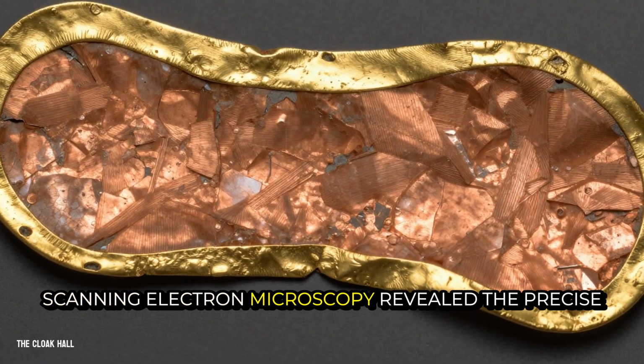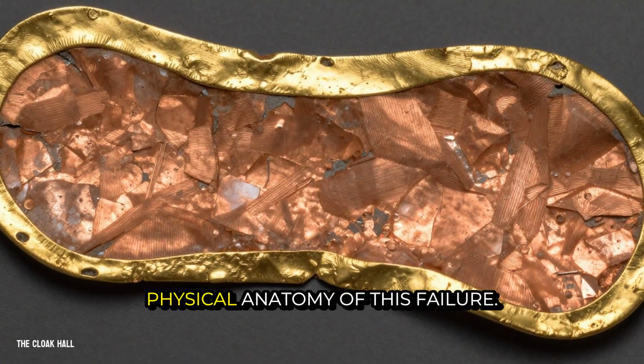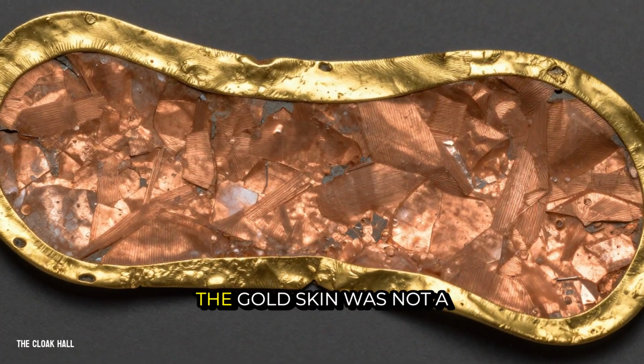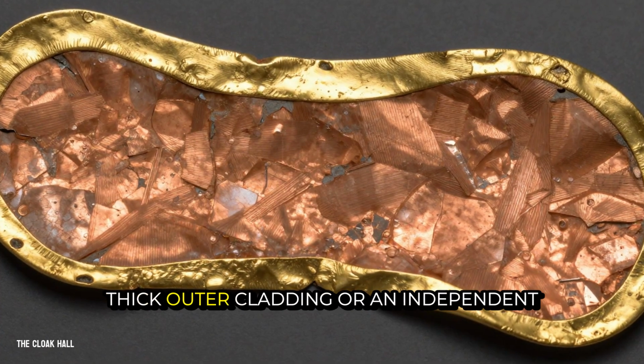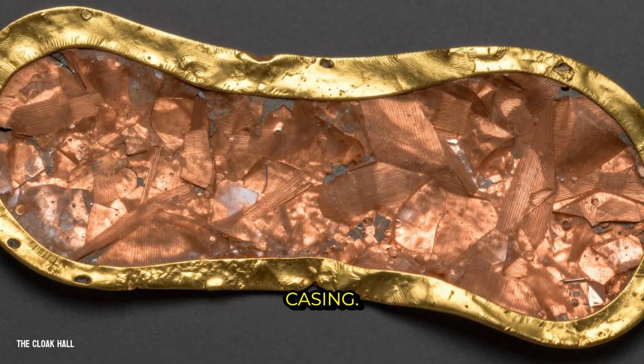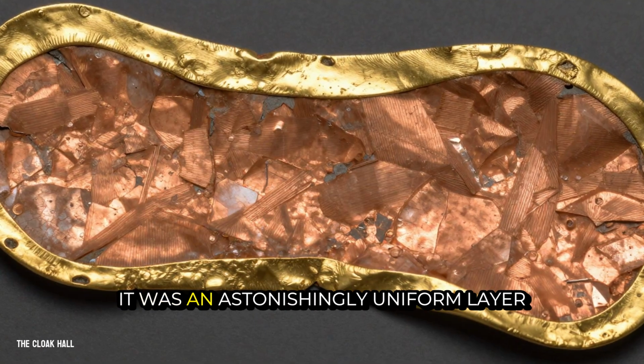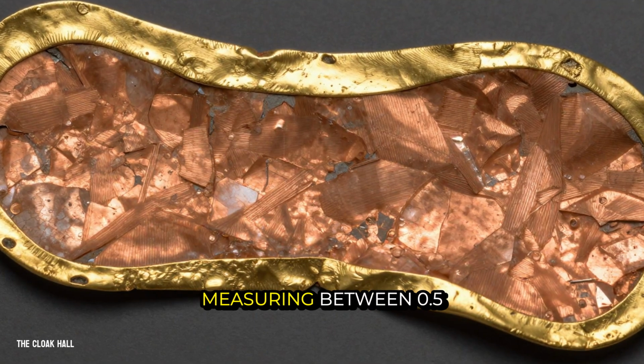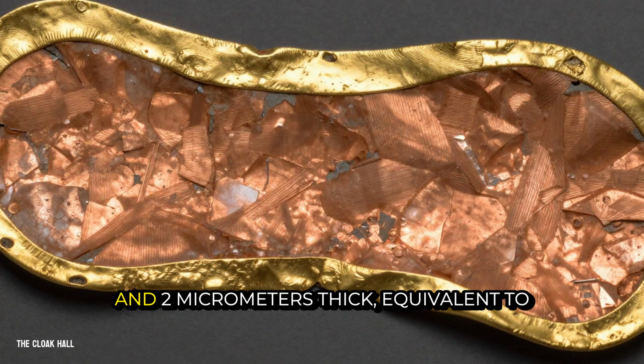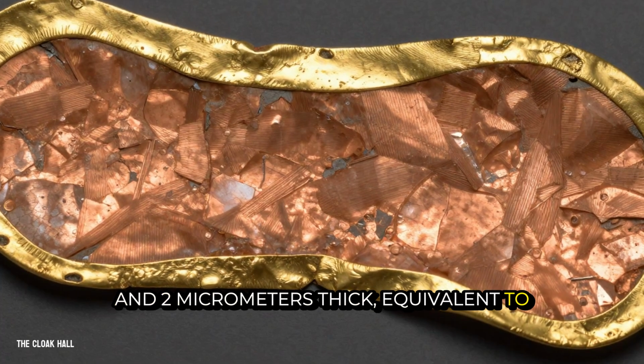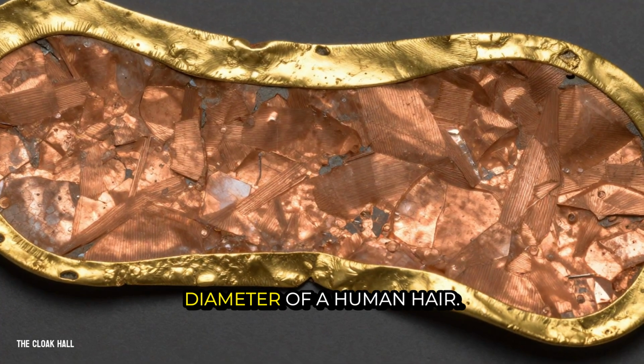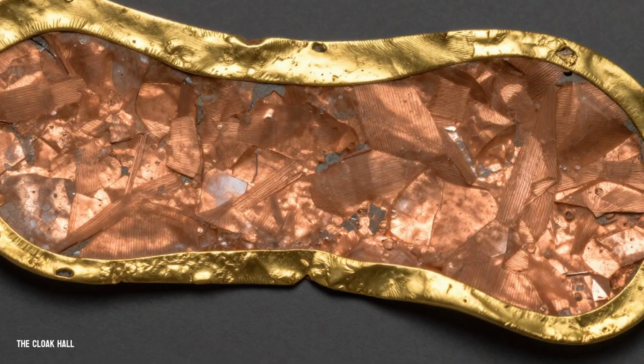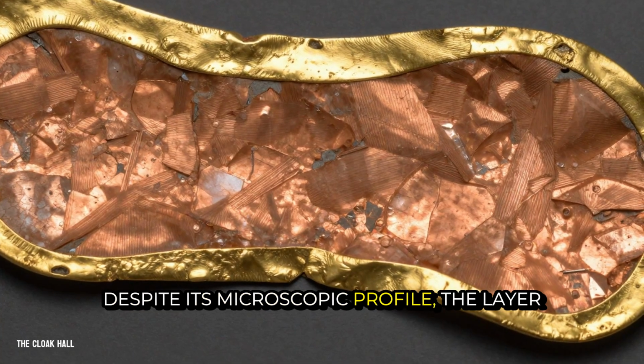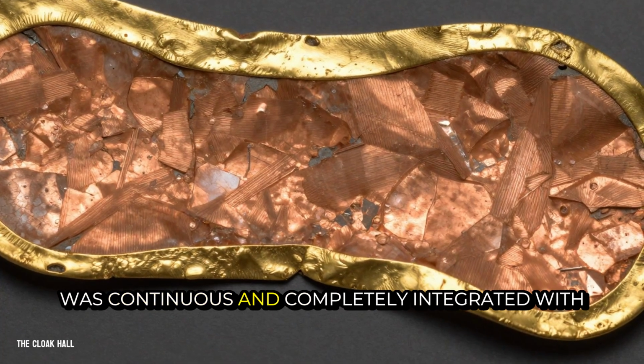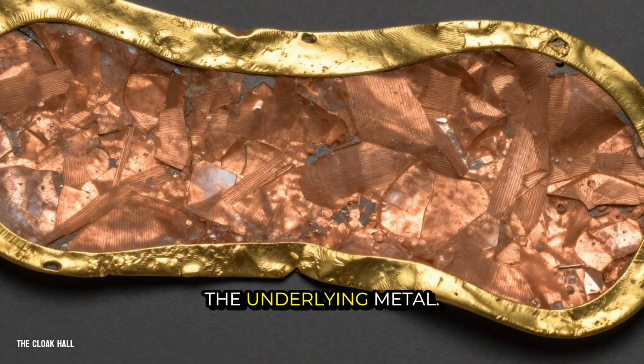Scanning electron microscopy revealed the precise physical anatomy of this failure. The gold skin was not a thick outer cladding or an independent casing. It was an astonishingly uniform layer measuring between 0.5 and 2 micrometers thick, equivalent to less than a 50th of the diameter of a human hair. Despite its microscopic profile, the layer was continuous and completely integrated with the underlying metal.